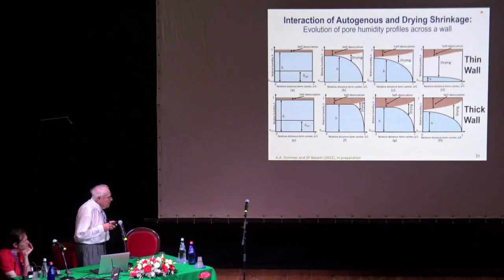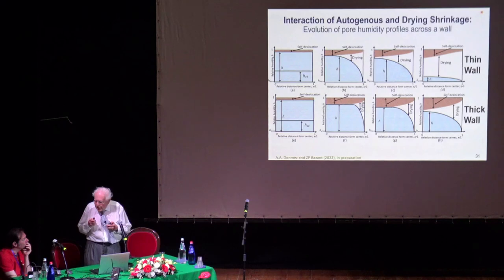Now, a complication arises: autogenous shrinkage. In old concretes, autogenous self-desiccation, the drop of humidity in the pores, or drop of chemical potential if you want, was only about 2%. Now, over the last 30 years, we reduced the cement content of concrete to less than 1/2. We are probably at the end of the road here.